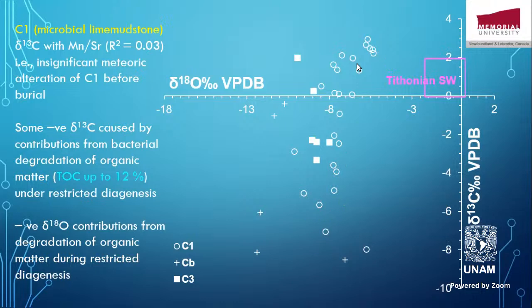And you can see, as I say, that there is overlap in the delta carbon 13 values, but for the delta O18 values, you can see that the Cb cement is a little bit more depleted than the C1, which is lime mud, and the fracture cement C3 is distinctively depleted in delta O18 because of the formation at high temperature. Well, as I said, for the delta carbon 13, we have manganese over strontium. With manganese over strontium ratios about 0.03, there is no correlation between the delta carbon 13 and the manganese versus strontium ratio. This means the delta carbon 13 ratio is preserved there.